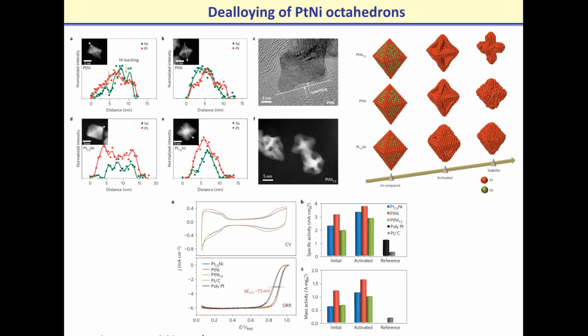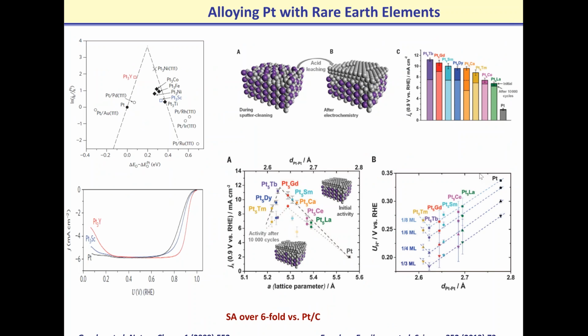So this is work from Peter Strasser, and he is known for careful observation of de-alloying. Of course, once you have atomic species that are not platinum as the initial point, they always serve as, I would say, active sites for dissolution or de-alloying, if you like, and that leads to different types of morphologies. And I would say the biggest challenge here is to which extent they're stable, because in each of those cases we are looking at some kind of skeleton type of surfaces.